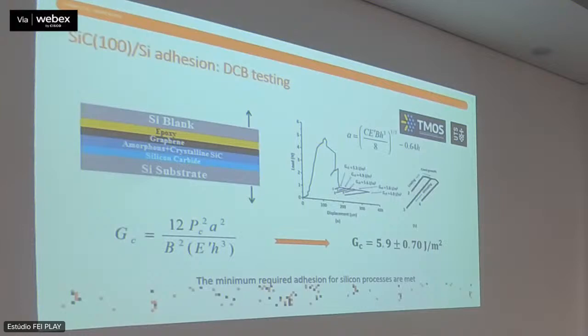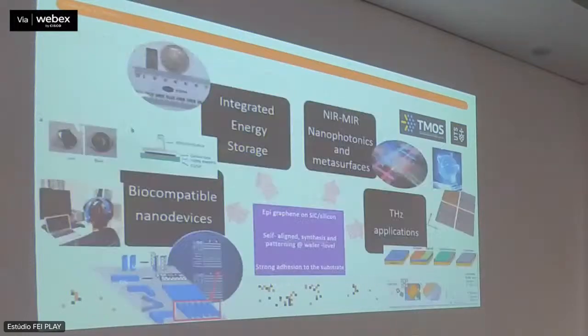You would never be able to get that type of adhesion if you had just flakes, which of course would be fantastic if you wanted high mobility layers. But if you want something integratable, at the other end, you also have to give in to some other sweet spot, basically. And I will show you that mobility is a different story, but in terms of productivity, which is the other very big drive for graphene integration into semiconductor processes, this won't make a difference.